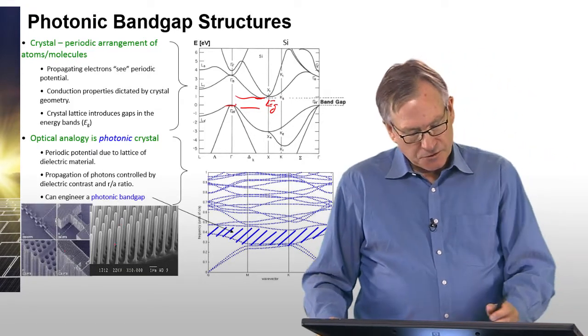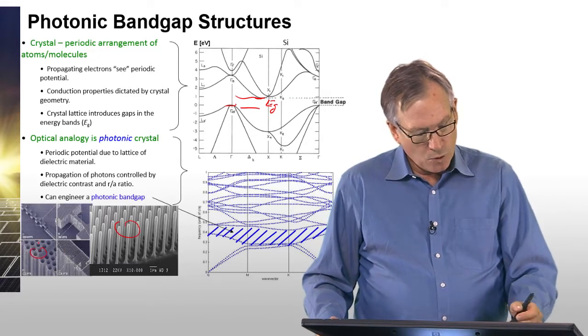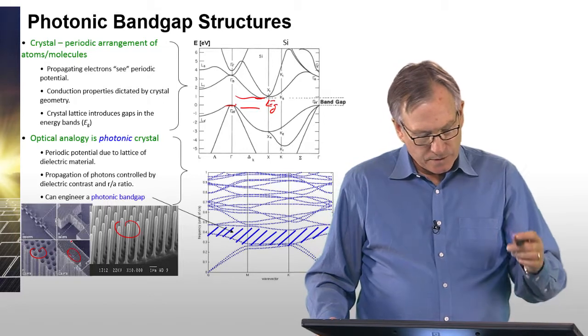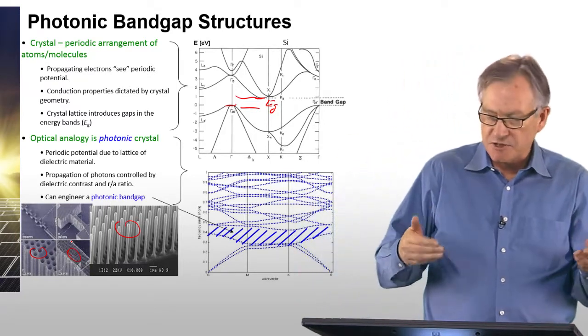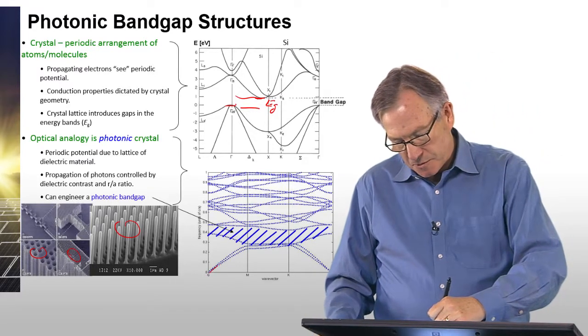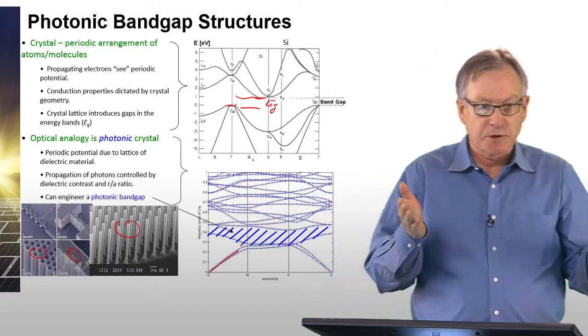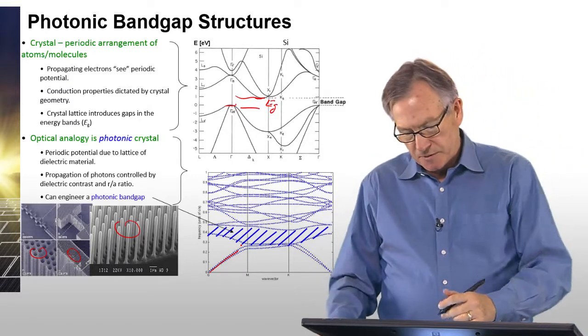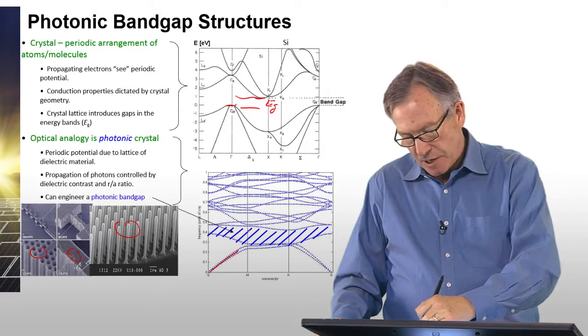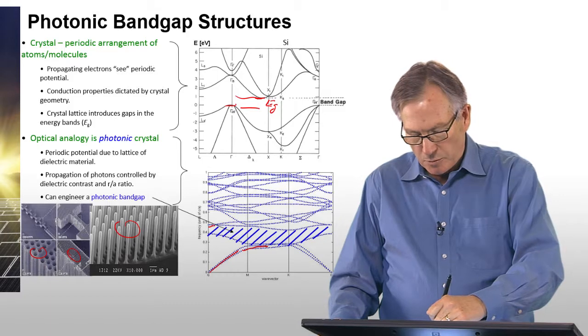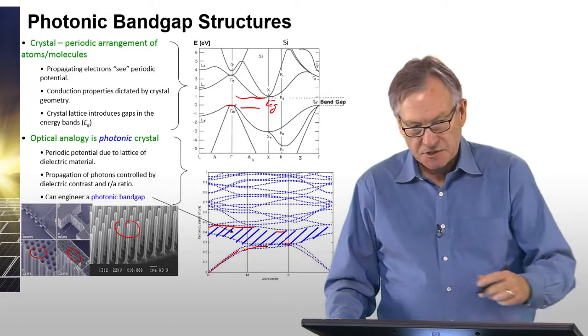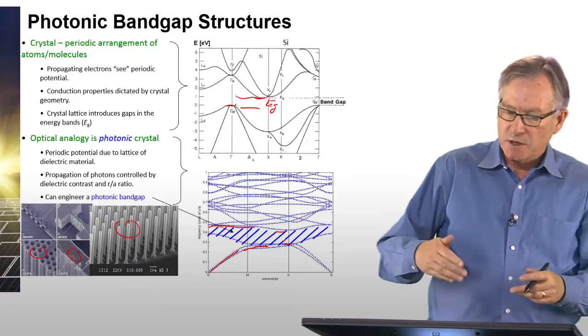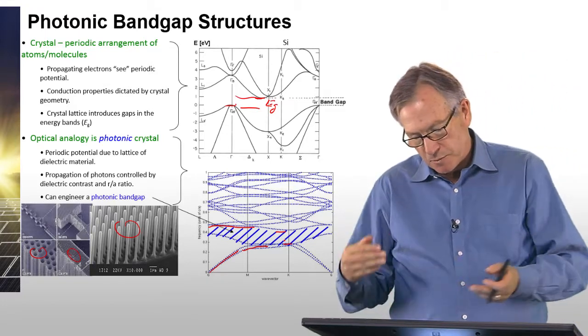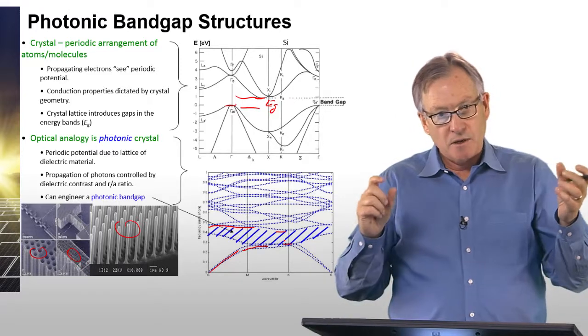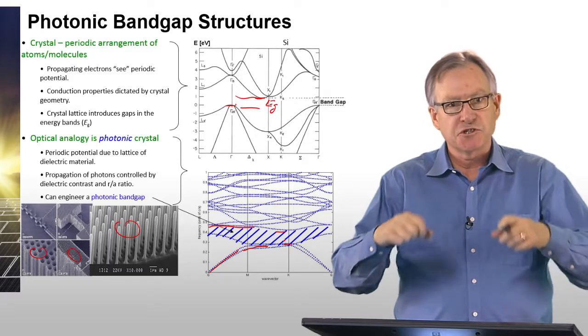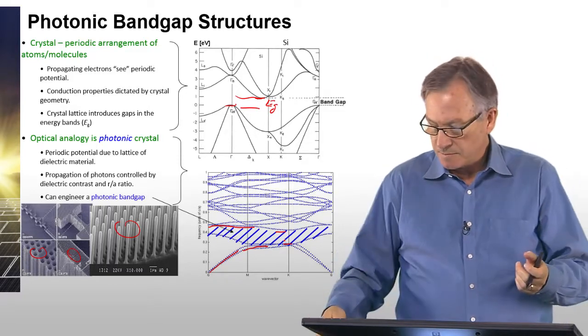Similarly, if you make an array of scatterers, and I've shown some examples down here in terms of nanowires, holes, arrays of etched holes, there are many different ways of making such structures. Normally the optical dispersion is a linear relationship, but because of the periodic scattering, you open gaps in the dispersion of light, and you have a bending over and new modes that start up here. There are gaps that are opened, and these gaps correspond to what are called photonic band gaps, in which you have no propagation of light. And so you can play with this spectrum and engineer the photonic band gap structure itself in order to capture more light into the semiconductor.